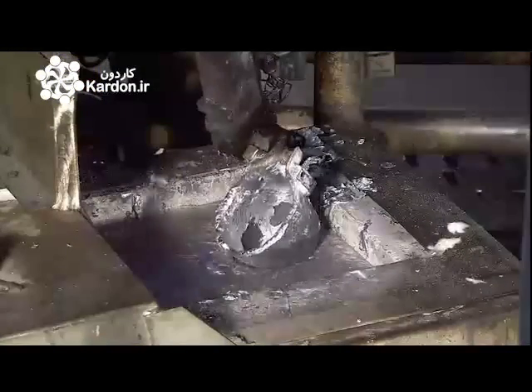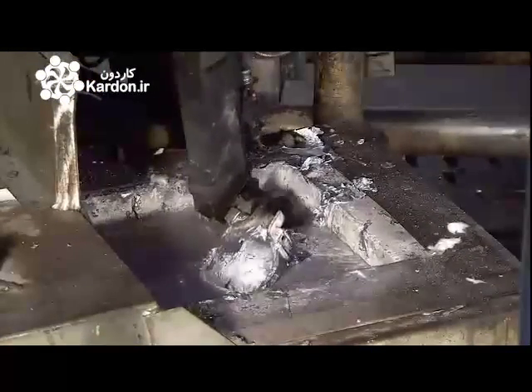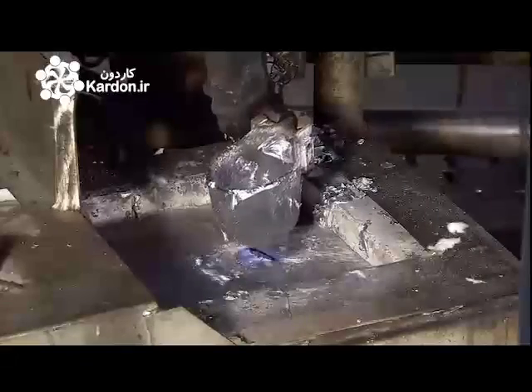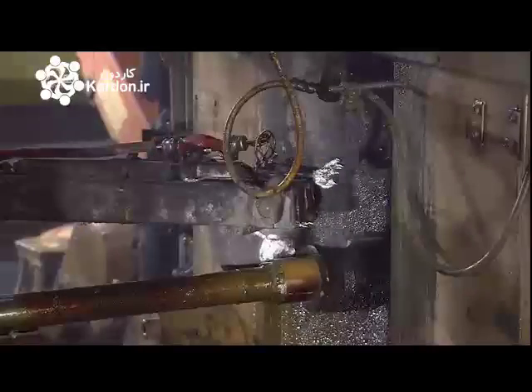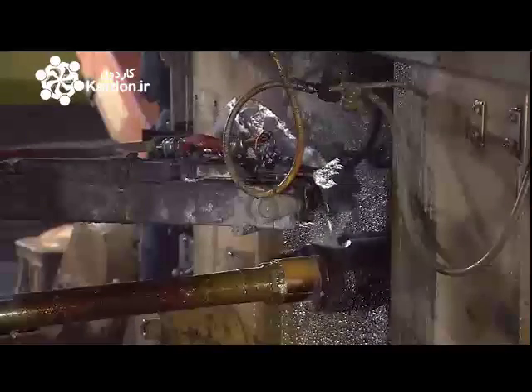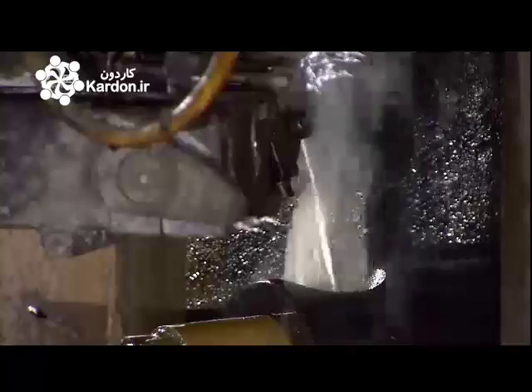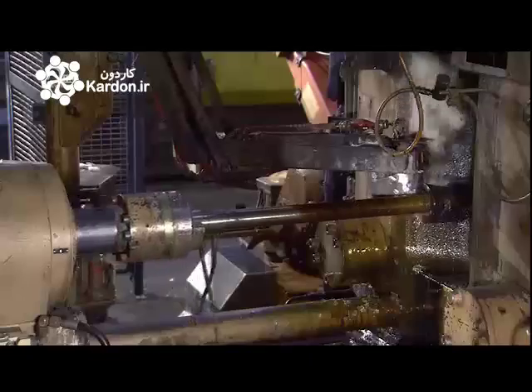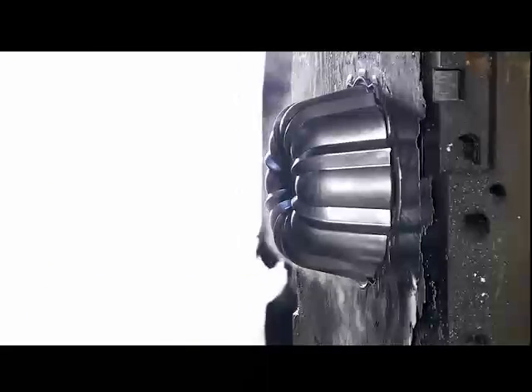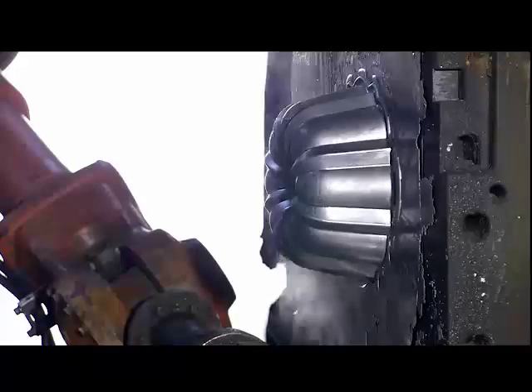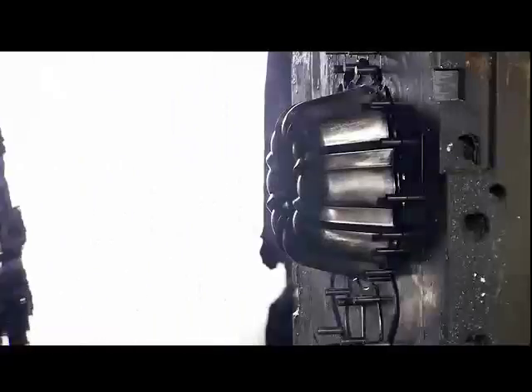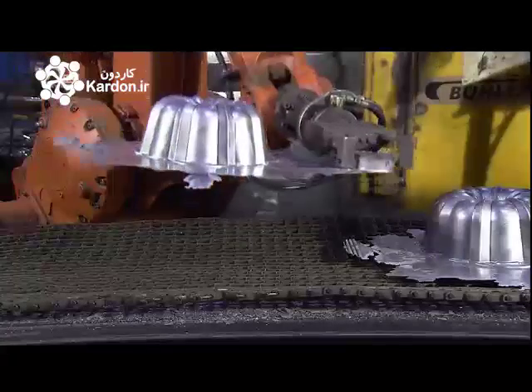The casting process is entirely automated. A ladle descends into the holding furnace and scoops up just under a kilogram of aluminium, enough for one Bundt pan. The molten metal then gets poured into a sleeve. A high-speed ram immediately pushes it into a Bundt pan mould. The pressure and speed combined shoot the molten aluminium into every part of the mould cavity. As the hot aluminium hits the cooler mould, it solidifies in about 10 seconds. Then the two halves of the mould automatically separate and the cast pan is extracted.